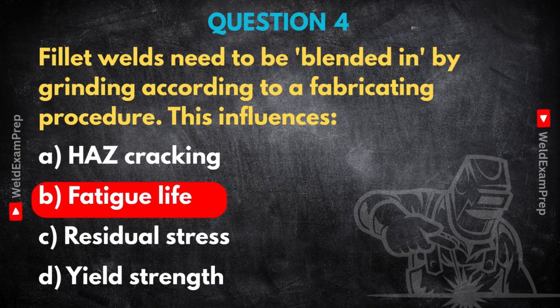By grinding or blending in that toe, you create a smoother, more gradual transition. You reduce that stress concentration significantly. So the stress gets spread out more evenly. Yes. Wow. Lowers the peak stress at the toe, which means it takes many, many more load cycles before a crack might start. Or it might prevent it altogether within the designed life of the component. It directly extends the fatigue life.